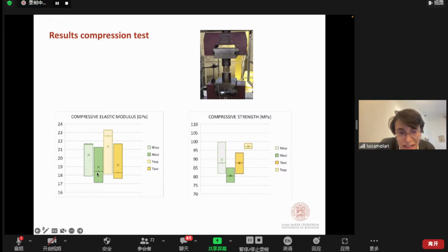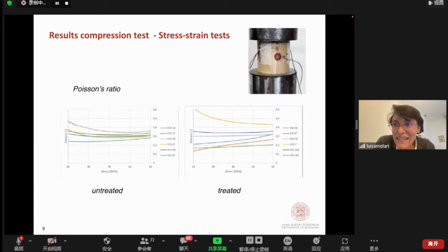There is some difference in the average value, but not statistically significant in the distribution. And for the compressive strengths, we can see more or less the same thing, because if we compare the darker with the darker and the light color with the light color, so the part that is from the bottom and the part that is from the top, each one with its corresponding specimens, we do not see much difference even in this case. The only thing that is quite different between treated and untreated samples is